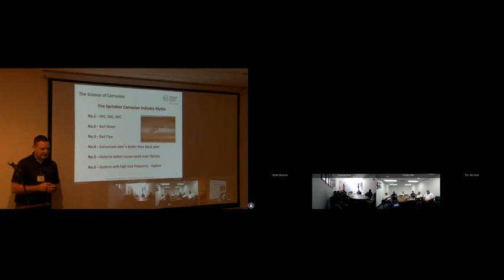And then number 6, it really deals more towards behaviors than the actual materials in the system. We've conditioned ourselves as an industry to think that we have to replace systems that leak a lot. What we're going to get into here in a second is that corrosion is highly localized, because we talked about how we need oxygen, we need water, and we need the steel. Well, the oxygen has to dissolve into the water to react with the steel. And oxygen doesn't like moving through water. It doesn't move very readily through water.